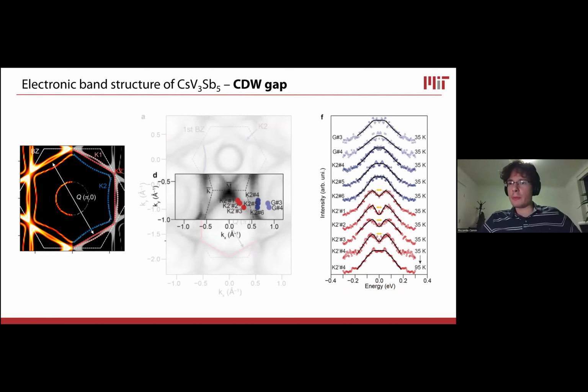I'm gonna go a little bit quicker now and summarize in a couple of minutes so we have time for questions. So for these K2 prime bands, we do see a gap that opens up at the Fermi energy, like a charge density wave gap. But this gap is not too big. It's of order 20 millielectron volts, which could make sense potentially.